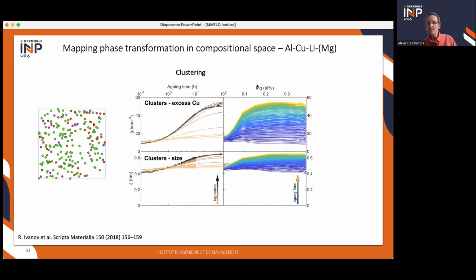So if you look here, how with aging time the clustering kinetics depends on magnesium, you see after a while that it becomes fast, more or less, when you have 0.1% magnesium, and it's slow if you have almost no magnesium. And so this was an interesting indirect effect of solute additions, which is that the presence of magnesium induces the clustering of copper. And it's a complex interaction between vacancies, magnesium, and copper.